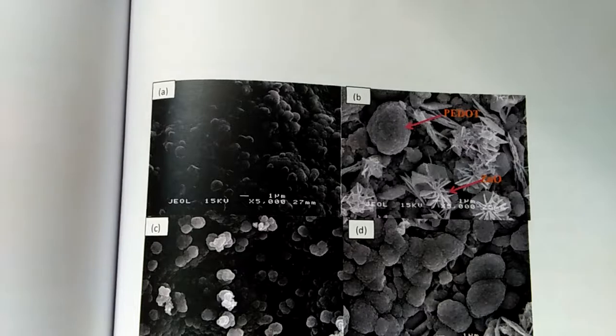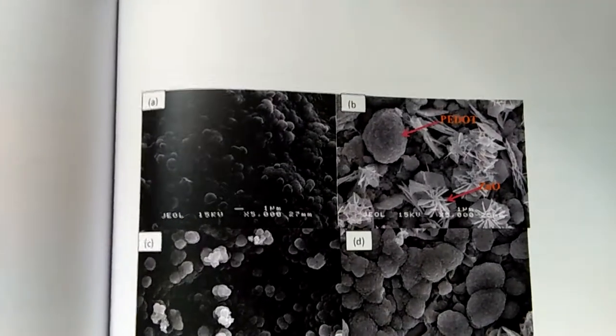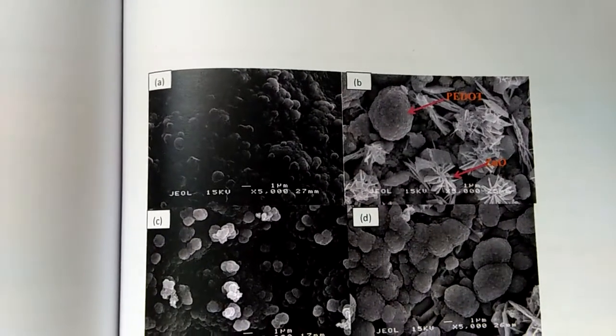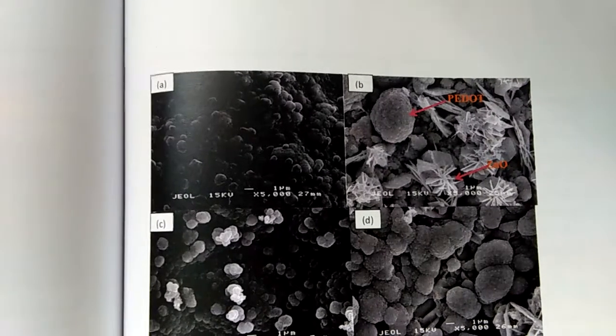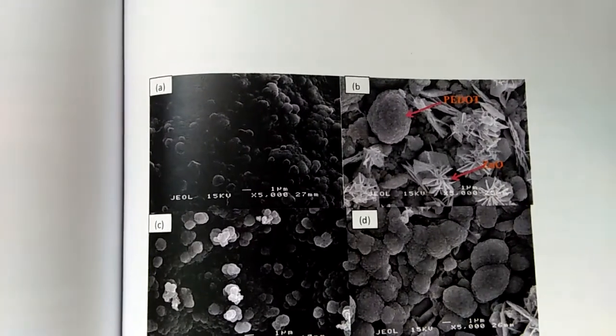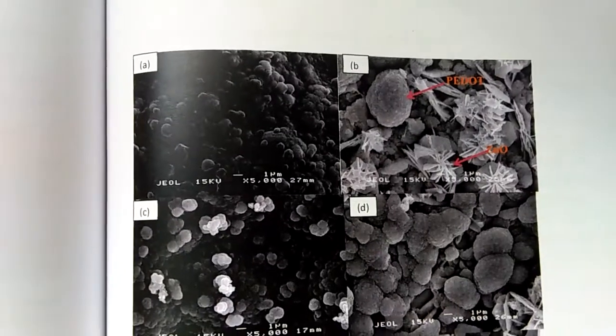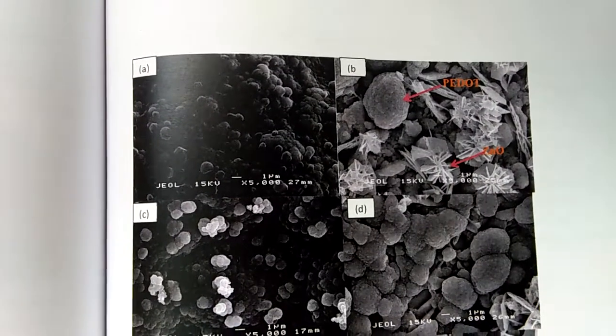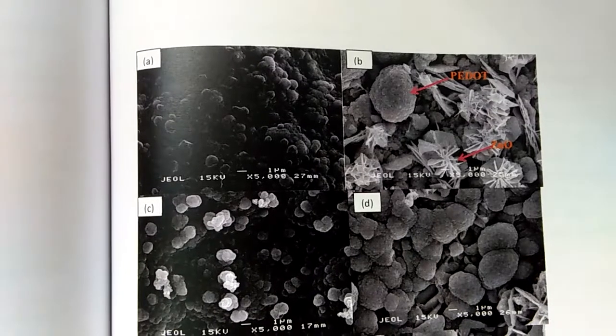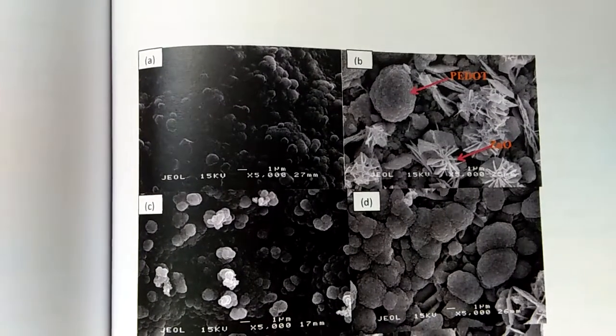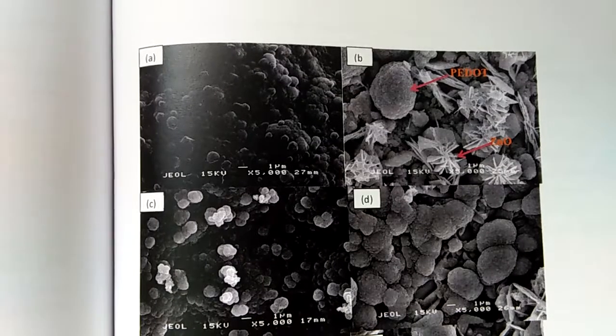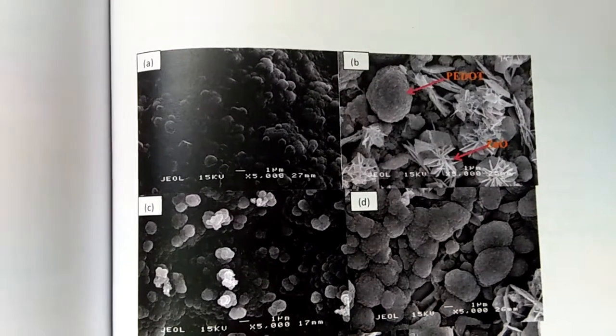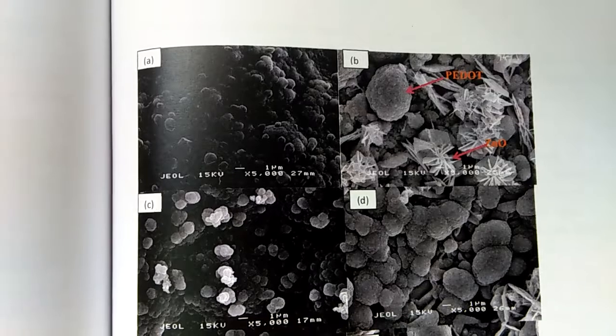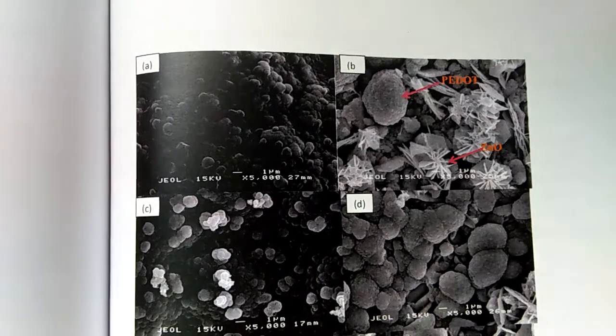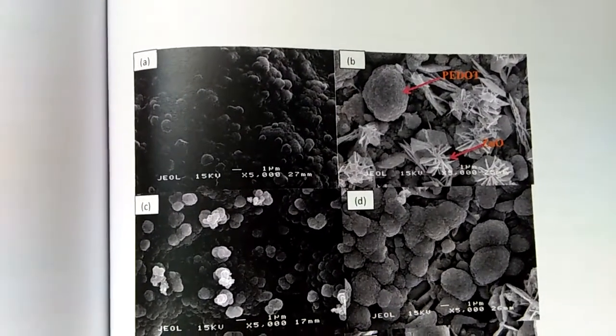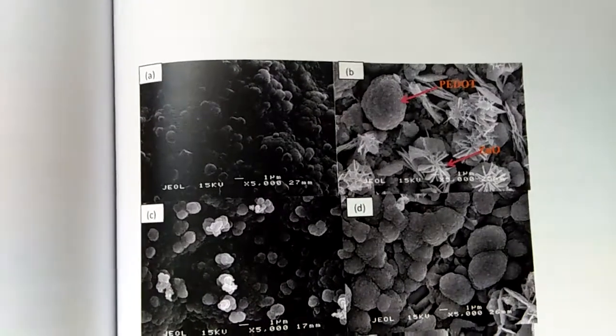So in order to produce this hybrid, you cannot use a one-step deposition technique because both of them require different potential and different conditions. If it only required different potential, you could use cyclic voltammetry to deposit it. But because both of them require different temperatures to deposit, one at room temperature, the other at high temperature around 80 degrees Celsius, you can't use a one-step technique. So you must use a two-step technique.